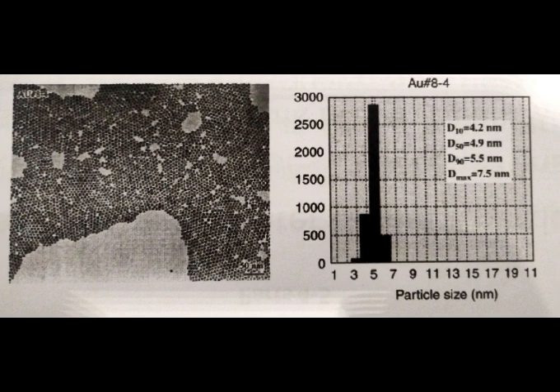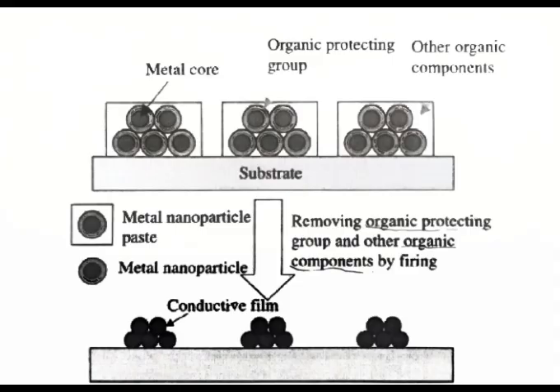And this uniformity is really important to get consistent performance in those conductive pastes. I see. And then the sub 10 nanometer size, that's also crucial because it allows for good dispersion, meaning basically that the nanoparticles spread out evenly within the paste. Think about trying to spread out large pebbles versus fine sand. Oh, okay. The finer particles are going to distribute much more uniformly, and it's essential for creating a smooth and consistently conductive film.